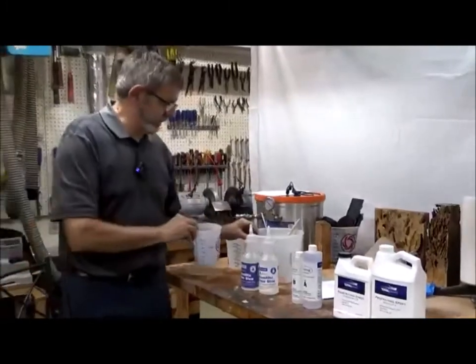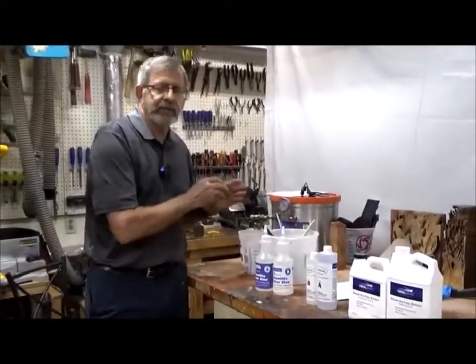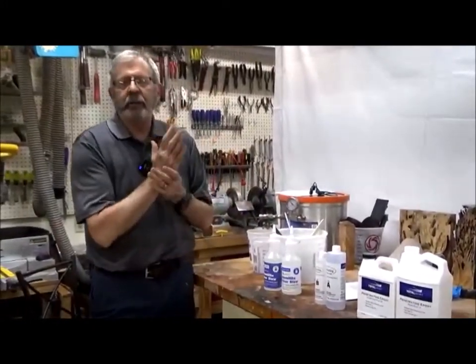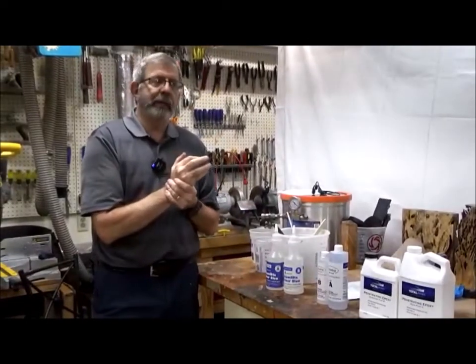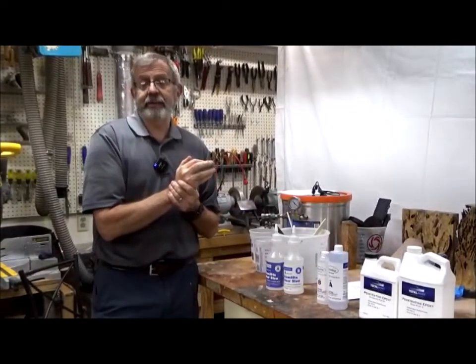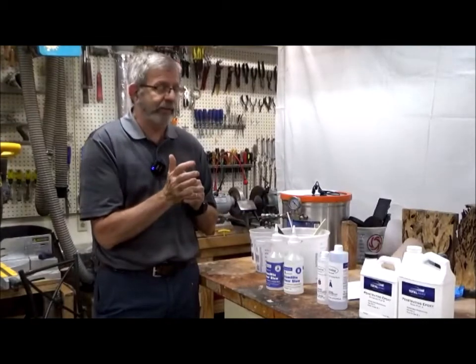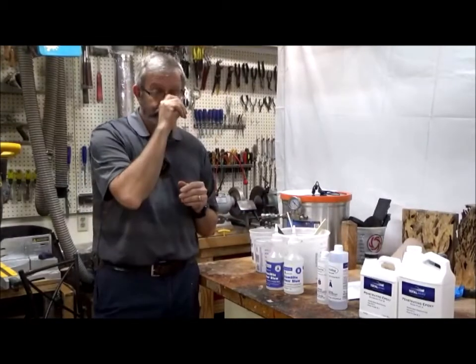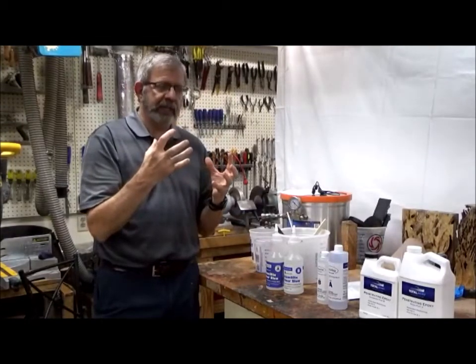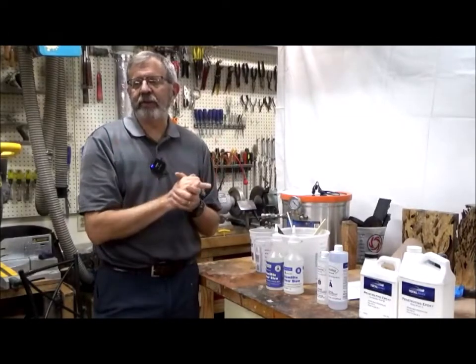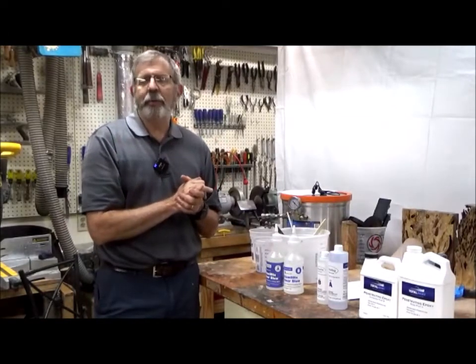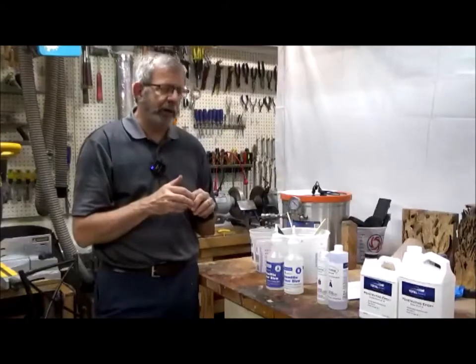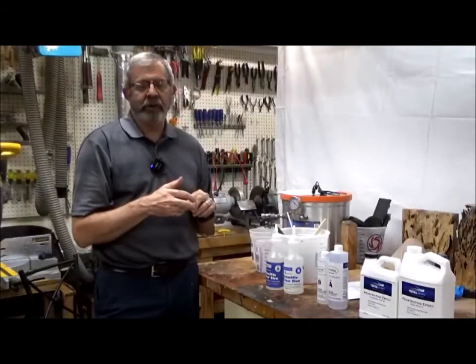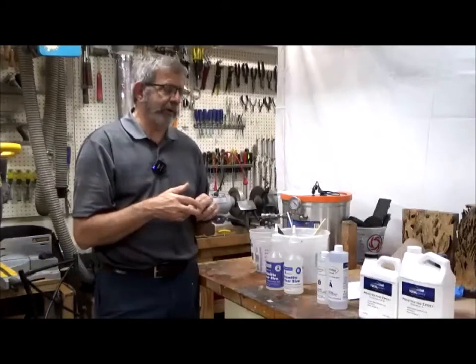I will show you a little later a picture of a piece of what happens when you don't mix it sufficiently. It either doesn't set, and you end up with soft spots in it, or it gets wavy inside the piece. You can see it's not homogeneous inside the piece. So it's very important that you mix it, particularly if you're mixing large volumes.